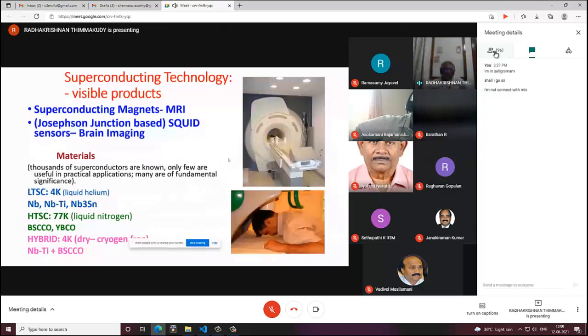Then you also have a combination hybrid thing. You have conventional superconductors, like we said, low temperature superconductors like NbTi and so on, and then combined with HTSC, high temperature superconductors like BSCCO. You must know that all superconductors have the property that the thermal conductivity is extremely poor in the superconducting state. So you can have a low temperature magnet using niobium titanium, and make the current leads of the magnet out of BSCCO or high temperature superconductor, keep that at 77 degrees Kelvin, so superconducting.